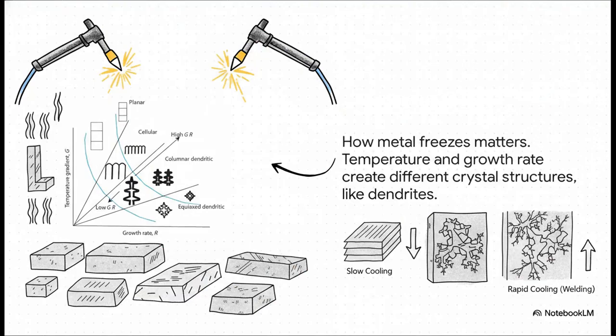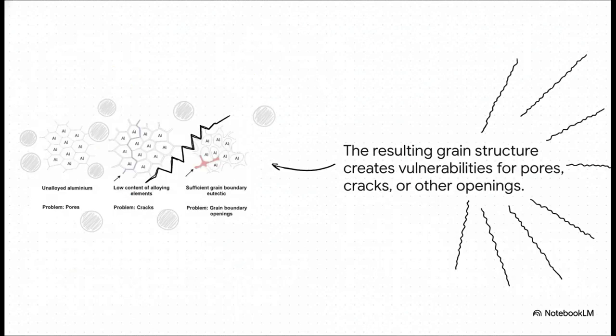You know, how this metal freezes is literally everything. This chart here shows the different ways it can happen. So depending on the temperature gradient, that's the G, and how fast the crystals grow, that's the R, you get totally different structures. If it cools slowly and steadily, you might get nice orderly planes. But in welding, it cools super fast, so you often get these complex, tree-like structures called dendrites. And hey, this isn't just academic. The kind of structure you end up with directly leads to real-world problems. For pure aluminum, you might get a bunch of pores. For other alloys, you can get these continuous paths between the crystals that are just perfect highways for cracks to travel down. The very blueprint of the metal can become a roadmap for failure.